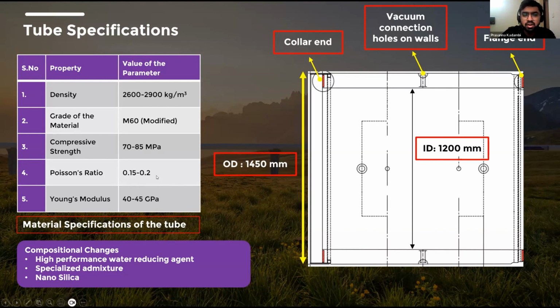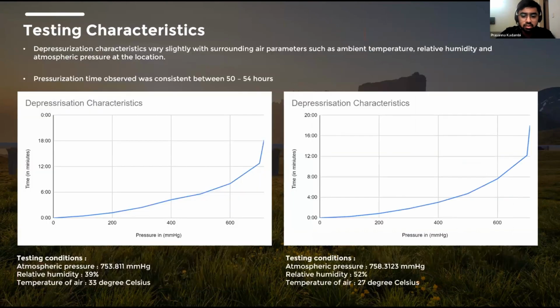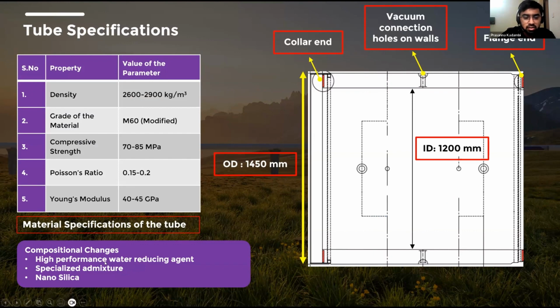So these are some of the parameters that we observed while we developed the entire material composition of the utilized admixtures as well as the other components. These are the significant compositional changes that we looked at as compared to the current options available in the market. I cannot really talk about the weight by weight percentage or weight by volume percentage for these compositions, but I can certainly tell you that these are some of the significant compositional changes that we have made. We have utilized a high performance water reducing agent fundamentally in order to lessen the porosity of the tube, and also to increase the compressive strength.